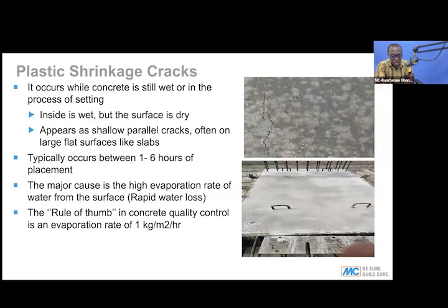Now, when it comes to plastic shrinkage, it is when you cast concrete and the surface is covered with a film of water. This film of water will definitely leave the surface, but that surface water has to be recharged by the water in the concrete itself. So, as the water is leaving the surface, other water from the concrete must also come to the surface to recharge it. But sometimes you have a loss of water on the surface that is more rapid than the rate of recharge from the water in the concrete itself.